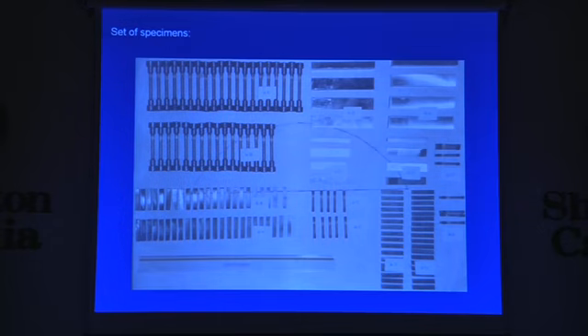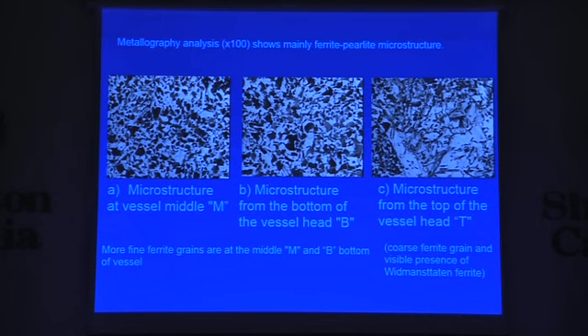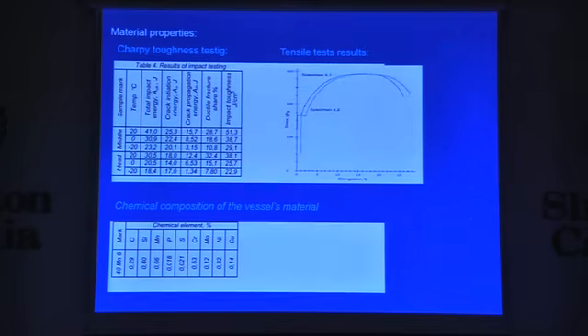So we have a set of specimens to characterize the material properties: the tensile test, the Charpy toughness test, and also fracture toughness testing according to standards. First, we also did some metallography on this inspection. We got some differences in microstructures regarding the place where the samples were taken, and this can also have some effect on the fracture toughness and other properties.